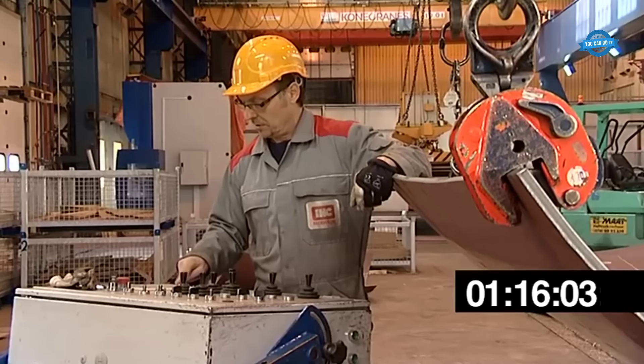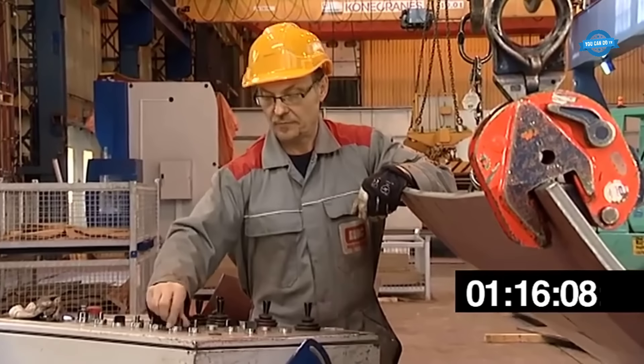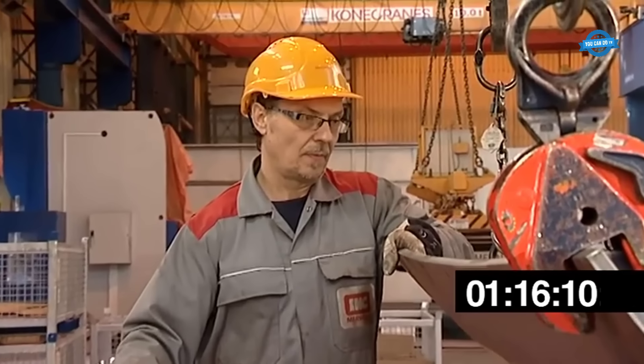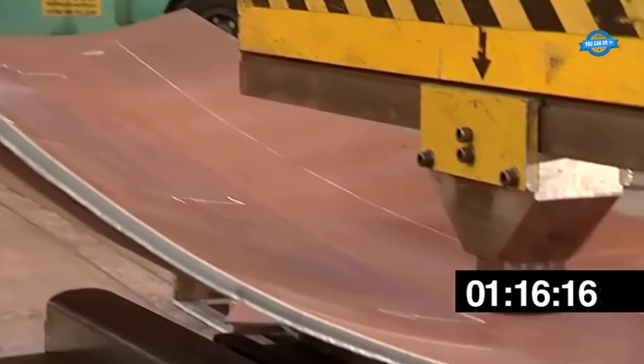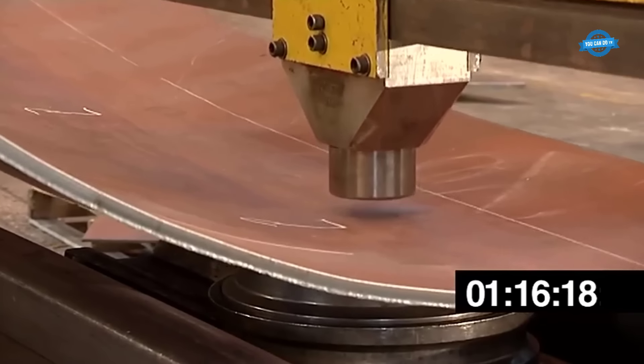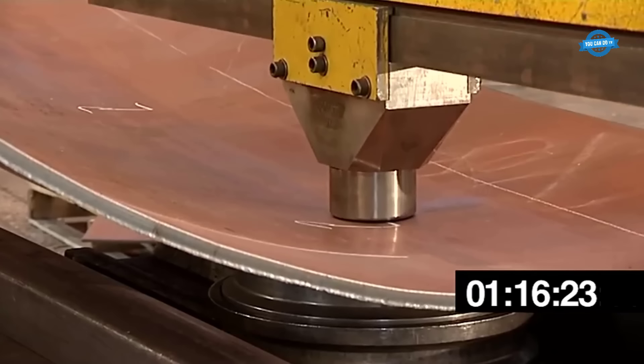The lines in the center of the bulbous bow are longer than the lines on the outside of the panel. For this, the bulbous panel is produced by giving center stretch first, and by rolling the center lines, the operator will soon get the basic shape for a bulbous panel. Getting the final shape is achieved by subsequent use of the shorter bending tools.